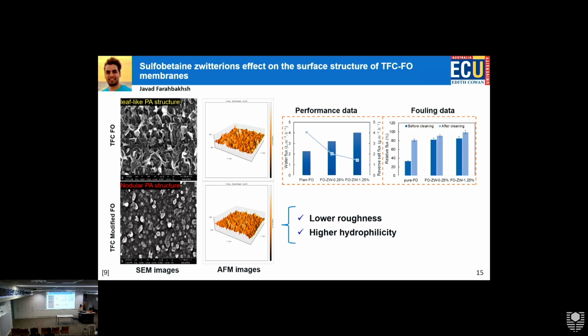So here again, normally after modification we have nodular type membranes, and the surface roughness data looks very similar, but the data showed that it was less rough, which is advantageous. The performance data is shown for 0.25% of zwitterions in the FO membrane and 1.25% zwitterions in the FO membrane again, and the plain membrane. We can see that water flux increased, which is advantageous. Reverse salt flux decreased. Reverse salt flux is the back diffusion of the salts to the feed.